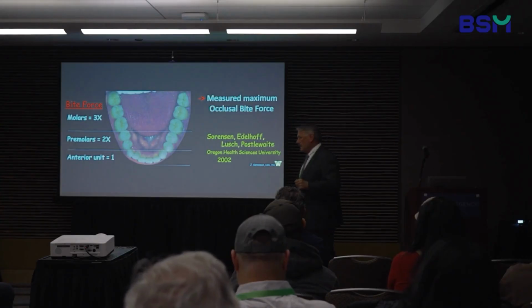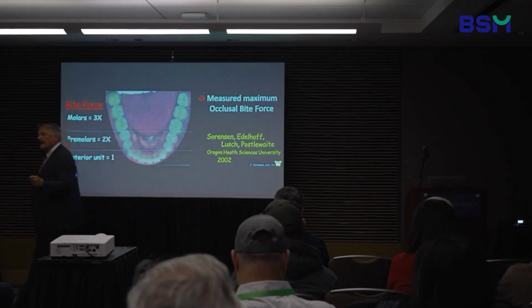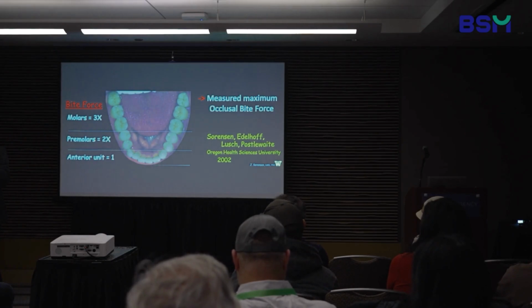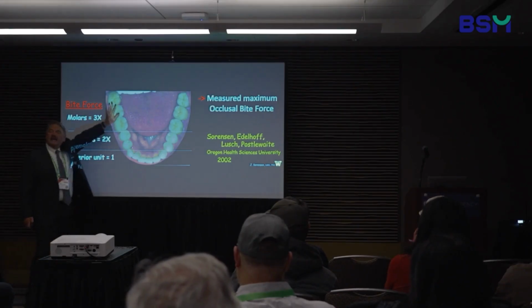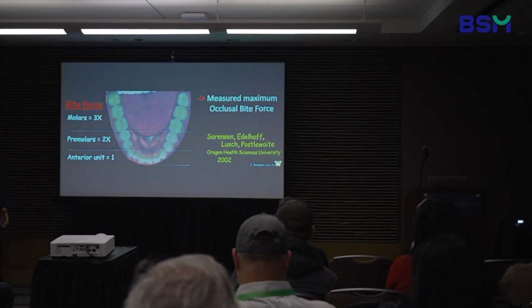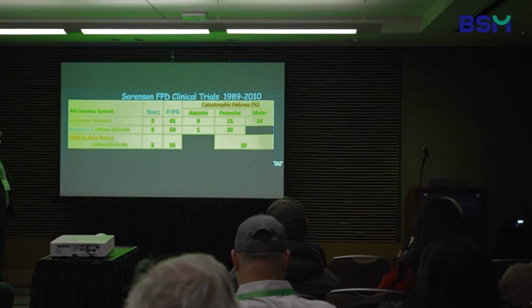In that study, we developed and invented a bite force measurement machine. If you take the bite force at the central incisors, we found in our measurements that at the second premolar it's double that bite force, and on the second molar it's 3 times. So obviously the forces on our posterior teeth are considerably higher, and if you want to use them for bridges, there are even greater stresses on that material. I have been working with a number of systems from the very beginning, back in the painful 80s with Cerestore and Dicor that had 35, 40% failure rates in the first year. So we were a little reticent to start using these materials for bridges. With In-Ceram Alumina and Empress 2, we're looking at a 10 or 11% failure rate, so definitely not strong enough for that.